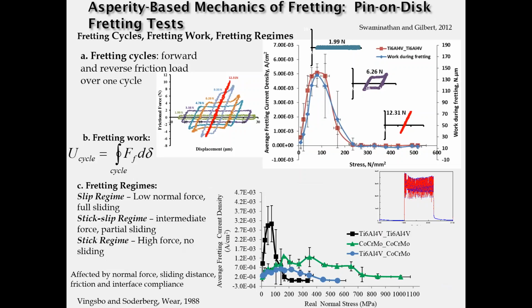So some of the results from our pin-on-disc tests have shown us that there is work done during a pin-on-disc fretting corrosion test where we're sliding back and forth and developing a frictional force over a sliding distance. As you raise the normal force in this pin-on-disc test, the sliding distance gets less because of the compliance of the system. And also, there is an energy dissipated, which is the work or the hysteresis energy within each of these curves, and that varies with the amount of load applied. As you get to very high normal loads, you essentially pin the pin on the disc, and it cannot slide, and you just get an elastic-like response.